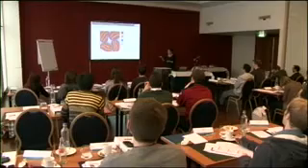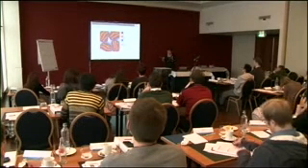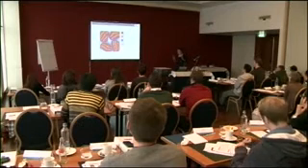Now, it is to a certain extent physically bound, but you can also, by drying very severely or heating up to even quite moderate temperatures, like 50 degrees or so, you can start to lose some of this water in this space. We then have water on the surface of these particles, which is assumed to be like a monolayer or 2 layers, or we don't exactly know.